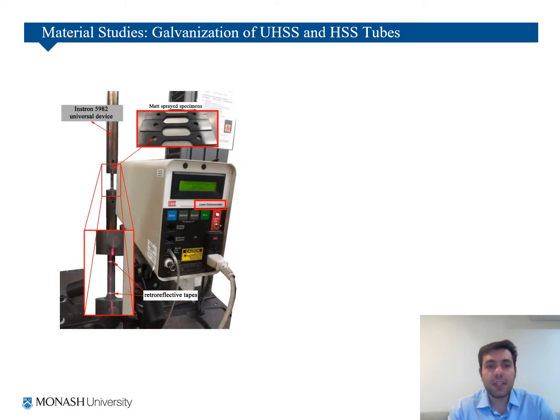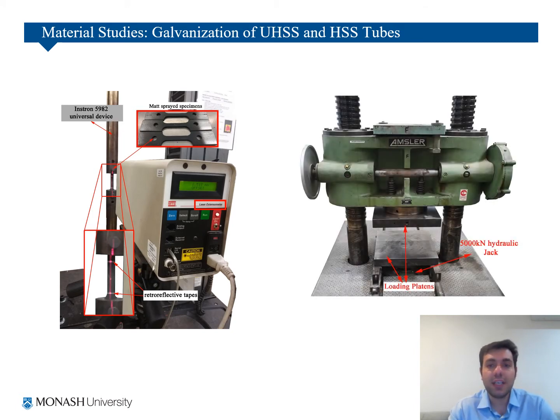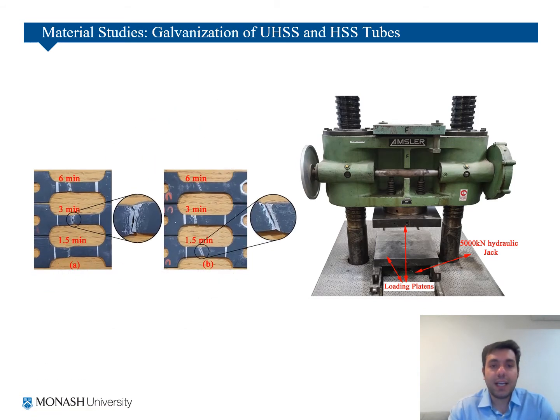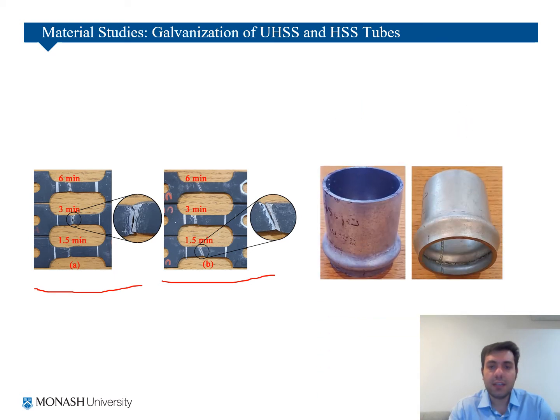Then we conducted some tensile tests on the coupons cut from these tubes after galvanizing, and some compressive tests on short tubes before and after galvanizing. As you can see here, these are the failure modes for high strength steels, and these are failure modes for ultra high strength steels, which are at an angle, so it's a shear failure behavior. And these are the compressive local buckling failure modes of all tubes.